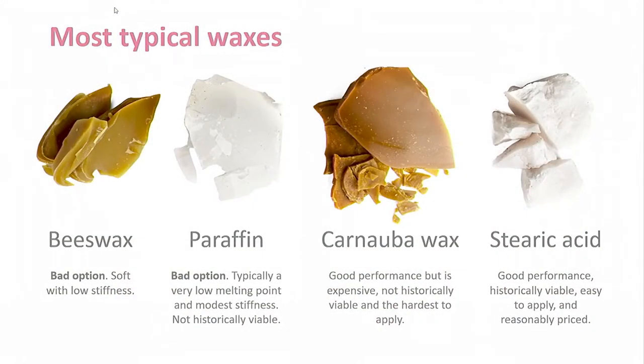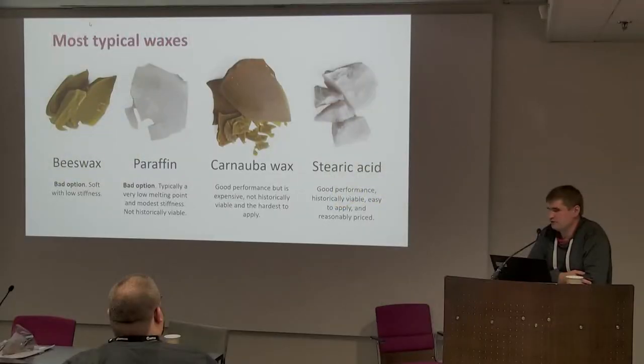Historically viable material, natural material. Good mechanical properties, easy to apply, and reasonably cheap material. Carnauba wax is the most expensive one of these. It has some practical problems. It's harder to apply. Stearic acid and beeswax are kind of similarly priced, at least in Finland, and paraffin is the cheapest. So the only reason you should use paraffin is if it's the only option you can afford, but not much better than that.